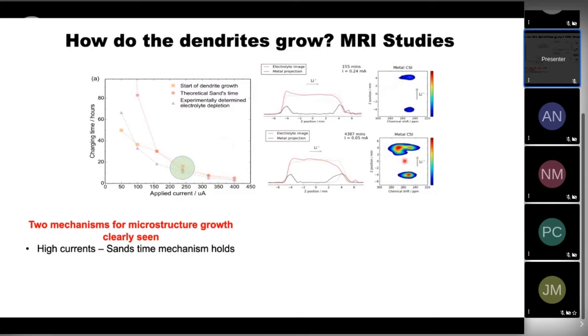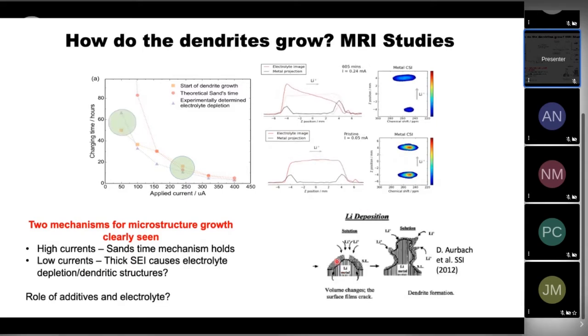But the problem, as shown in this image here, is that you still grow dendrites. And the reason for that is this continual formation of this passivating layer that I was discussing, or the SEI, that forms this inhomogeneous or heterogeneous coating where some parts of the coating have gaps that are exposed and some are much more resistive. And that creates, again, a structure that promotes dendrite formation. And so the challenge now is to improve both our understanding of this SEI and to make a smoother SEI.